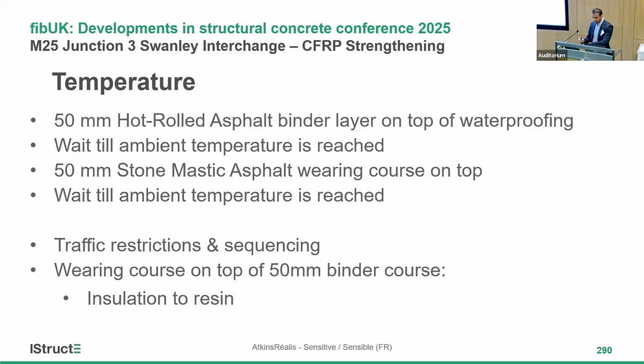Then we waited till the ambient temperature was reached. And once the ambient temperature was reached, we laid another 50 mm of the wearing course on top of this binder layer. Then again, we waited for the ambient temperature.